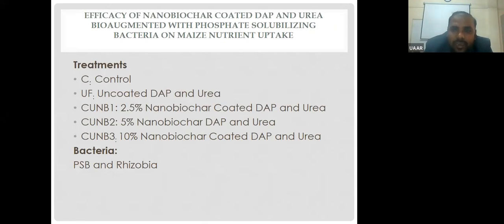Next is efficacy of nano-biochar coated DAP and urea bio-augmented with phosphate solubilizing bacteria on maize nutrient uptake. And here also we used control, uncoated DAP and urea, and then coated nano-biochar with 2.5, 5, and 10%. And we also added phosphate solubilizing bacteria and rhizobia. We coated these urea and DAP with farmyard manure nano-biochar at 2.5%, 5% and 10% to DAP and urea, and added both of them at 50-50%.